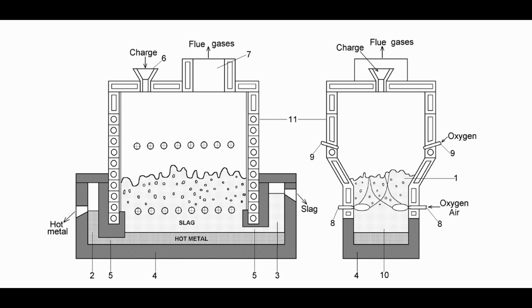In the slag bath, the heat expense on melting and reduction of the charged materials is greater than the heat received from the burning of carbon into carbon monoxide near the lower tuyeres. Thus, the main peculiarity of the process is the post-combustion of carbon monoxide, hydrogen, and coal volatile matter evolving from the bath by the oxygen blown through the upper tuyeres. Post-combustion of the gas up to carbon dioxide and water allows returning the heat into the slag bath and maintaining processing of raw materials.